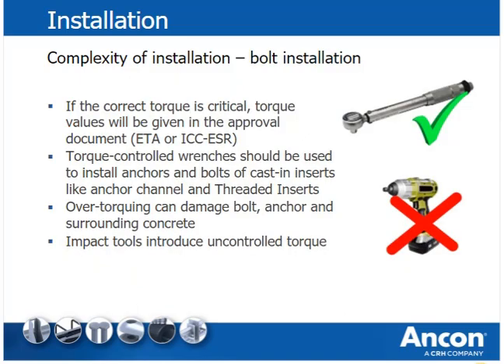For most anchors, including threaded inserts, it is important that the anchor is not over-torqued during installation, as high torque can introduce loads that exceed anchor capacity and might damage the bolt, the anchor or the surrounding concrete. The use of torque-controlled wrenches is highly recommended. Electric impact tools, so-called rattle guns, can introduce very high loads and thus damage the anchor.